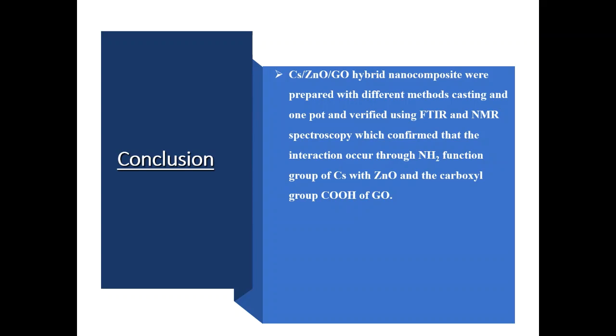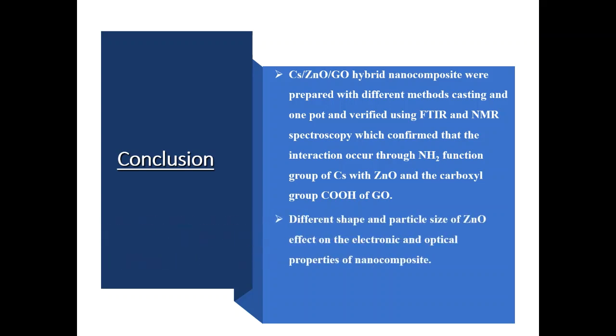Finally, we can conclude our work as follows. Zinc oxide graphene oxide hybrid nanocomposites were prepared with different methods, casting and one-pot, and verified using FTIR and NMR spectroscopy, which confirmed that the interaction occurs through the NH2 functional group of chitosan with zinc oxide and the carboxyl group of graphene oxide. Different shape and particle size of zinc oxide affect the electronic and optical properties of the nanocomposite. Also, one-pot is the ideal method for preparing chitosan zinc oxide graphene oxide as optoelectronic material.